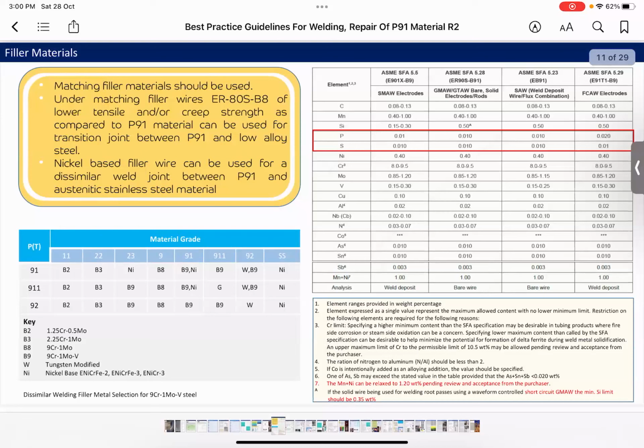These elements, in addition to silicon, of course, have a low melting point. So this low melting point during welding can create hot cracking. So it should be noted that phosphor and sulfur should not exceed 0.01%. The other two elements that should be monitored, as I said earlier, are manganese and nickel.